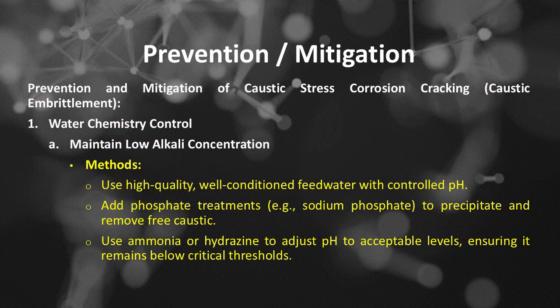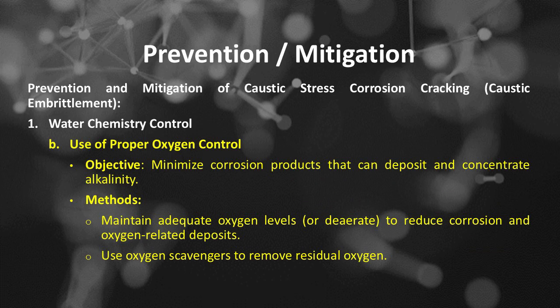Methods that can be used to maintain low alkali concentration include: use high-quality, well-conditioned feedwater with controlled pH, add phosphate treatments such as sodium phosphate to precipitate and remove free caustic, use ammonia or hydrazine to adjust pH to acceptable levels, ensuring it remains below critical thresholds. Number B of water chemistry control is use of proper oxygen control. Its objective is to minimize corrosion products that can deposit and concentrate alkalinity.